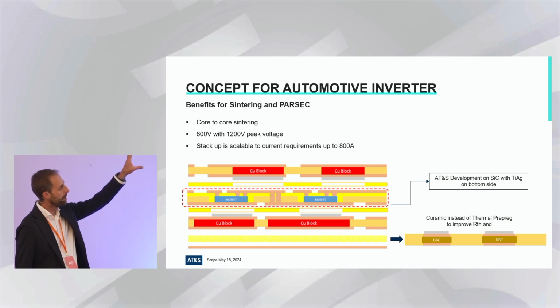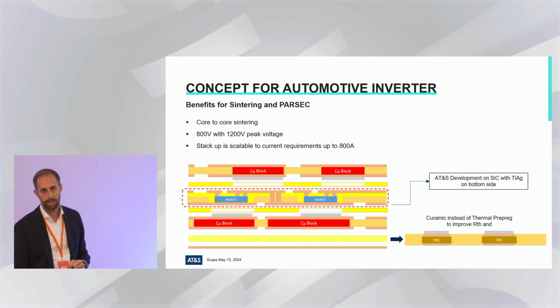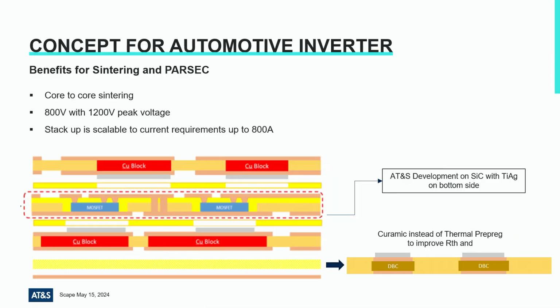So here you can see the standard cell in the middle, which is the BASIC approach. And then we have one core on the top side, one core on the bottom side, which allows you to carry the current on one side, but also allows you to do the cooling. And there we can do single-sided cooling. We can also do double-sided cooling. The benefit with this construction is that you have, from the symmetry of the stack-up, quite good values. So you're not significantly different, which creates a lot of warpage. So with the symmetry, there comes also the reliability.